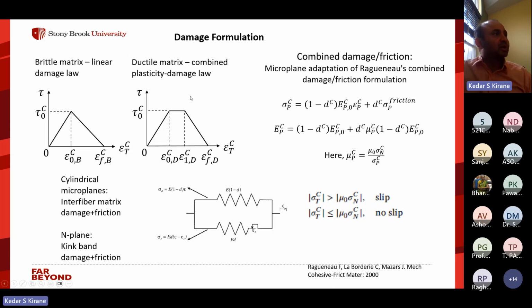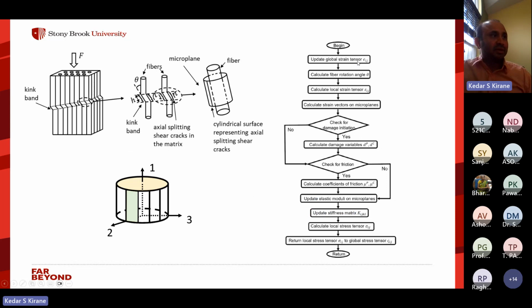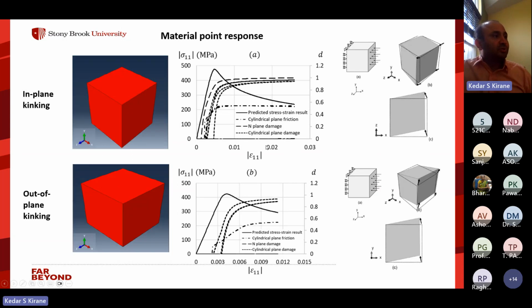Okay. So to summarize, basically we take the macroscopic strain tensor, then we rotate it by the angle theta, then we project it onto the microplanes, then we check for the damage. It can either be linear softening or trapezoidal, and check for the friction and calculate the friction coefficients. And using this, we can update the elastic moduli if there is damage. And then using those, we can update the stiffness matrix to get the stress tensor. And whatever is the rotation, it is again updated here. So the system keeps rotating. Okay. Now for some results.